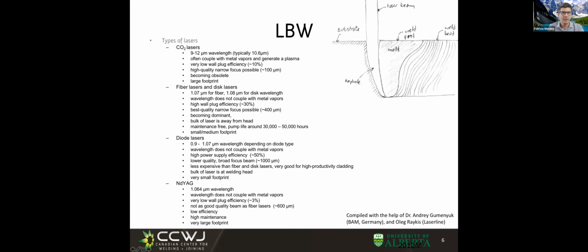So they have an advantage though, and that is that they can have a very narrow focus. When you want to weld with lasers, you want to have a relatively narrow focus. You don't want to have a very big area of light because it all gets reflected. But if you have a narrow focus, you can create this keyhole, and this keyhole has relatively high efficiency because as the light bounces in this molten part, it's hitting the walls and acts as a cavity that is like a black body cavity. It's not a black body, but it's a lot darker than shiny metal.